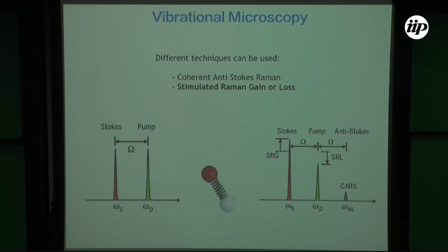That's called the stimulated Raman gain or loss, okay? So when the two lasers go into the sample, there is an energy transfer that's mediated by this vibrational mode. So the pump laser can lose some intensity. It can lose photons. And the omega S laser can gain some photons, okay? So basically there's an amplitude change on your input lasers, both on omega P and omega S, okay? The problem is how we detect this, because we are pumping the sample with this laser, and we want to detect some amplitude difference, which is very small. So the laser noise usually is much larger than the expected intensity difference here, okay?